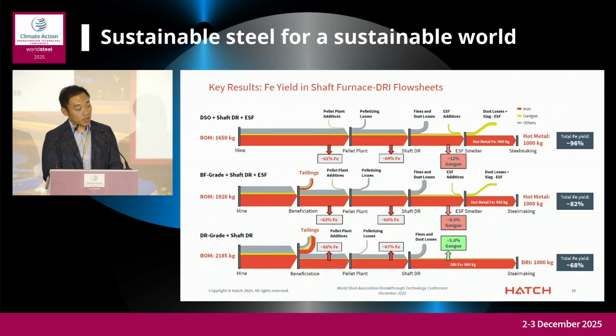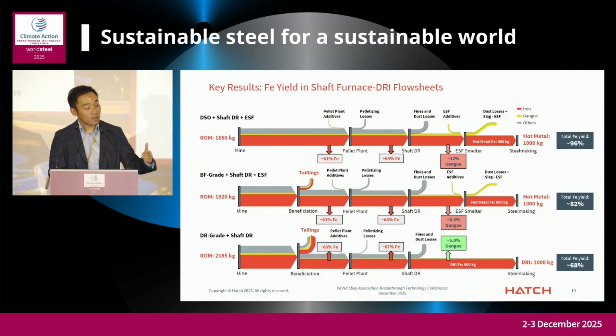Next slide, which I think is the key results. Comparing, at the top, run of mine from the Pilbara iron ore going through pelletizing, shaft furnace reduction, and then going to ESF for gangue rejection, producing roughly a ton of hot metal, versus the middle, which is doing BF-grade beneficiation, and the bottom, of course, beneficiating intensely all the way to DR-grade, in which case the product is about a ton of DRI. So 1 ton of equivalent ore-based metallics.